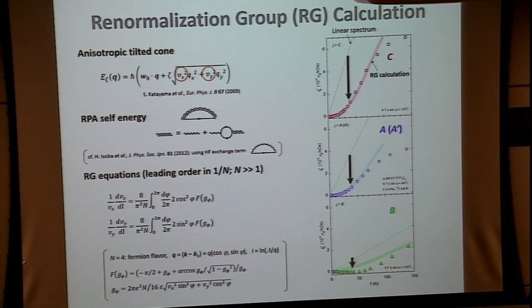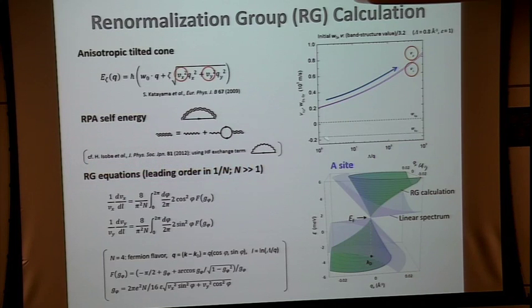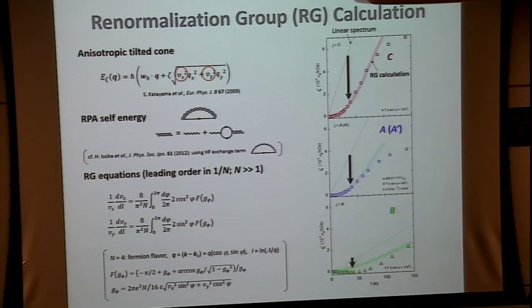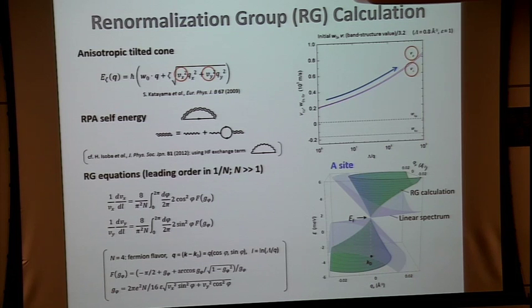They obtained the result. This red curve, blue curve, and green curve is a result of the renormalization group calculations. Vx and Vy is renormalized like this. It's gamma over q. Q is a wave vector in the first Brillouin zone. So as q approaches 0, it means that energy is decreasing, so the velocity is increasing logarithmically. And this cone is a result which fits the experimental data like this here. So we conclude that this transparent gray cone is the band structure calculation.